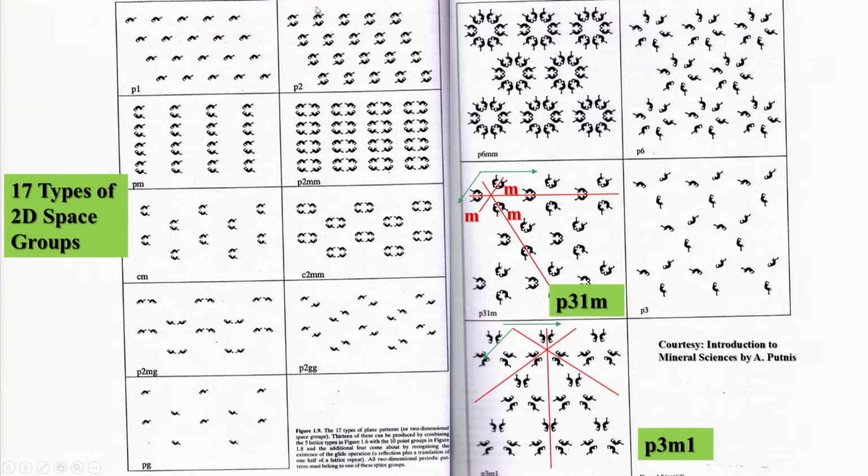So, let us now come to this particular arrangement here. So, what do we have here? Let us consider this is the dinosaur here and let us consider the presence of a two-fold axis of symmetry here. So, what will happen here? This vertical two-fold axis will act on the first dinosaur and will generate another dinosaur of this orientation here. This pair now can be translated along this direction and along this direction, this A and B. These repeat units are unequal and the angle between A and B directions is not equal to 90 degree.